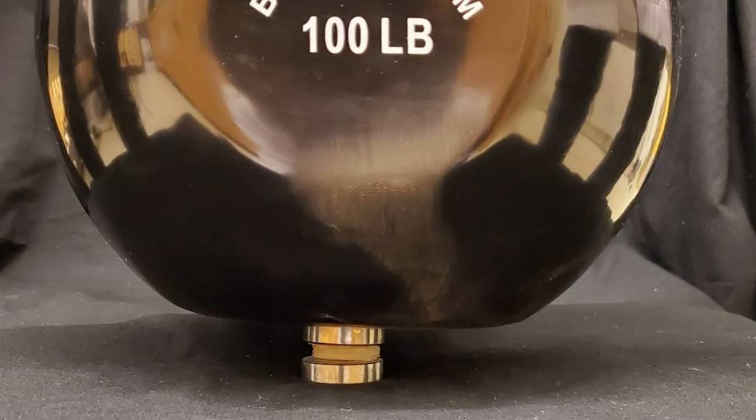In one experiment, the team subjected it to 100,000 cycles of repeat pulling, and the material held up just as well as porous titanium used for bone implants. They also rubbed the new material against natural cartilage a million times. They found that its smooth, slippery, self-lubricating surface is as wear-resistant as the real thing, and four times more wear-resistant than synthetic cartilage implants currently FDA approved for use in the big toe.